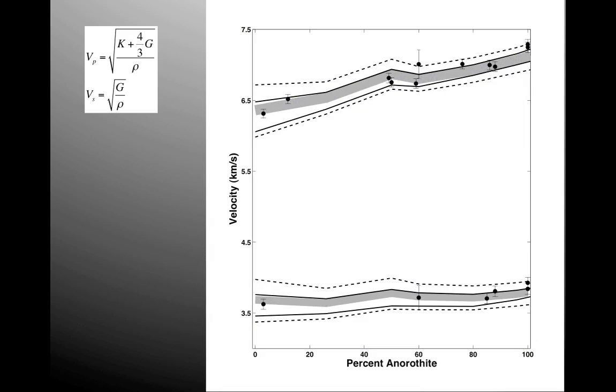And the compressional velocity is a function of bulk modulus and shear modulus, and the shear velocity goes as the shear modulus. In this diagram, the circles are measurements on rock aggregates that are all or almost all feldspars. These come from a variety of sources. The largest data set for the compressional velocities is from the famous paper by Francis Birch in 1961. Additional work by a number of authors has added a few more points to this diagram, as well as the shear wave velocities.